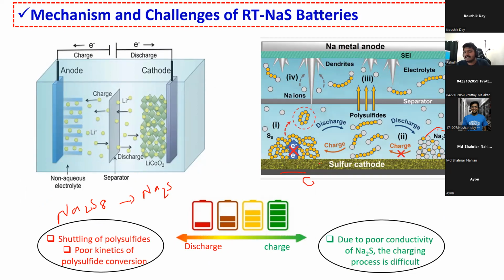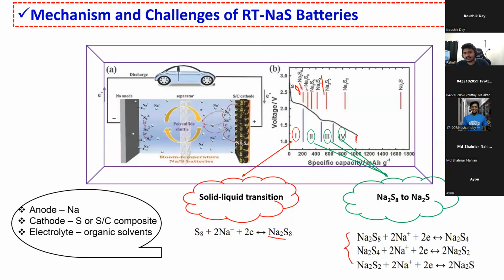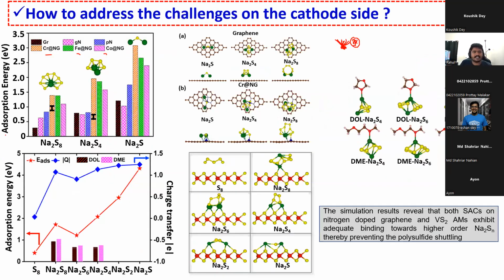Basically, if we use any carbon-based material, it won't bind this polysulfide. Again, because of the interaction energy between the polysulfide and electrolyte, it will go to the electrolyte rather than staying in the electrode. Now, we actually proved that from our DFT calculations. This is the interaction energy between the electrolyte and the sodium polysulfide, and this is the interaction energy between our carbon or graphene and the polysulfide. You can see that the interaction energy between the carbon and the polysulfide is very low when compared to the interaction energy between the electrolyte and the polysulfide. So since the interaction energy is higher between the electrolyte and the polysulfide, it will go to the electrolyte rather than staying in the electrode.